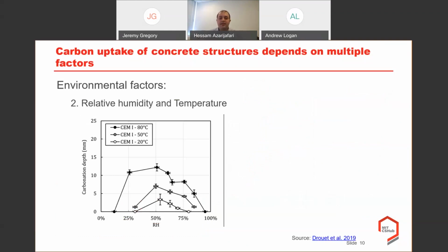The second environmental factors that I would like to talk about is the relative humidity and the temperature. The relative humidity and temperature both influence the carbonation depth significantly. As you can see on this graph that shows the carbonation depth on y-axis and the relative humidity on x-axis, the increase in the temperature from 20 degrees Celsius to 80 degrees Celsius would significantly increase the carbonation depth. But the other important factor is the relative humidity that you can observe in x-axis.